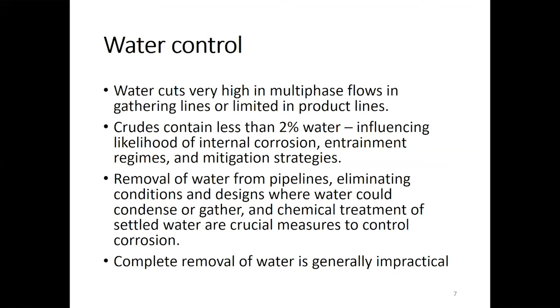Water control, water cuts could be very high in multi-phase flows, and especially in the initial stages of the piping system, in the gathering lines, and could be limited in stages in the product lines. And crudes in general could contain as much as 2% of water, but they to a great extent influence the mechanism, the likelihood of internal corrosion, and also could change the entrainment regimes, the flow regimes, and in the end dictate the mitigation strategies.